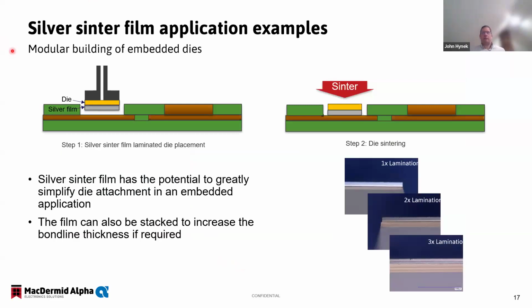Another interesting application we've been seeing a little more is what we call embedded dies. We'd like to believe that film is a very good solution to this application. And the reason is, like I showed before, it's a very accurate placement of film. And if there's a really tight tolerance in an embedded die application, you can see here in this corner where this tolerance could be really short, it would be very difficult to get paste to work well in this spot. So what you would do is you can use your film, sinter it onto the die, and then attach it to your substrate.